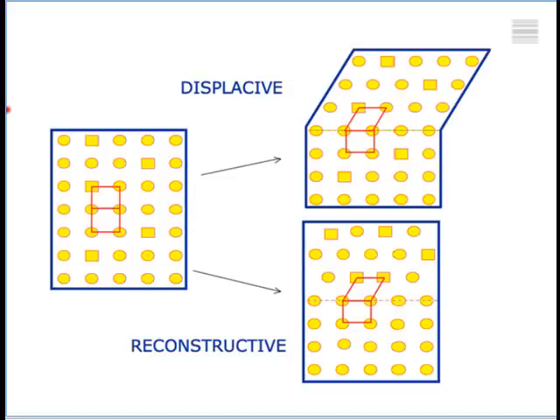I can change the way in which these atoms are arranged into the crystal structure of ferrite by two different mechanisms. One is that I deform this structure so that I generate a new pattern without the need for atoms to diffuse. Diffusion means an uncoordinated movement of atoms. So here, by physically deforming the crystal structure into a new pattern, we've got the crystal structure of ferrite. But there is no diffusion, so you'll see that the number of square atoms here is exactly the same as the number of square atoms here. So this kind of transformation can happen at low temperatures. And bainite, martensite, acicular ferrite, all of them, we call them displacive transformations because you achieve the change in crystal structure by a physical deformation, which has a large shear strain. It does not require diffusion for those reactions to happen.